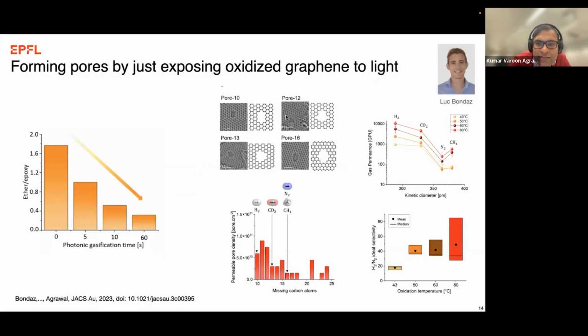Here are some pictures of how these holes look. These are aberration corrected transmission electron microscopy images. What you're seeing is really the atoms of graphene organized in a honeycomb lattice, and in between we have removed atoms by gasification or by oxidation. So these are the different pores that we form. Looking at an ensemble of these holes, what we have is essentially a pore size distribution, pores characterized by a number of missing carbon atoms. Most of these pores are permeable to hydrogen and CO2, and very few pores are permeable to nitrogen and methane.